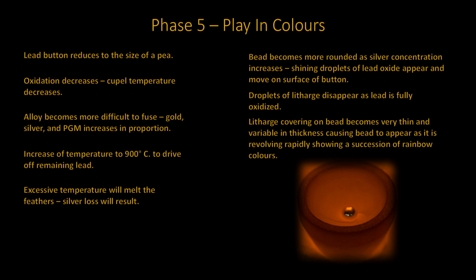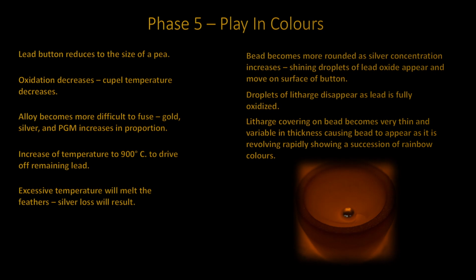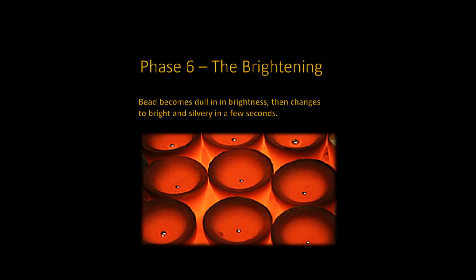During this process, the lead oxide covering the bead will become very thin and variable in thickness. The bead will appear to be revolving rapidly in the Cupel and will show a succession of rainbow colors. This interference effect of light is referred to as the play of colors. When that display of the play of colors disappears, and it will very quickly, that tiny pea-sized bead will become dull in brightness, but will, after a few seconds, become very bright and silvery in color.